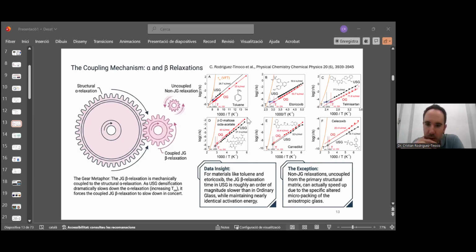So what we see in the ultrastable glass is that this Johari-Goldstein beta relaxation, which we can measure in the glass, okay? We don't need to go to the liquid to measure them. So these relaxations are slower in the ultrastable glass with respect to the ordinary glass, okay? And it makes sense, no? Because if you have a denser system, it makes sense that the molecules are slower in their movements, no? So that's why this kind of relaxation is slower.